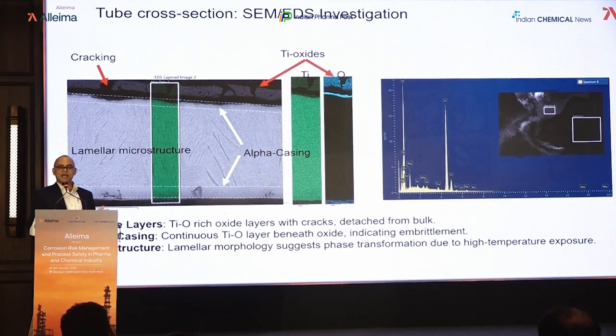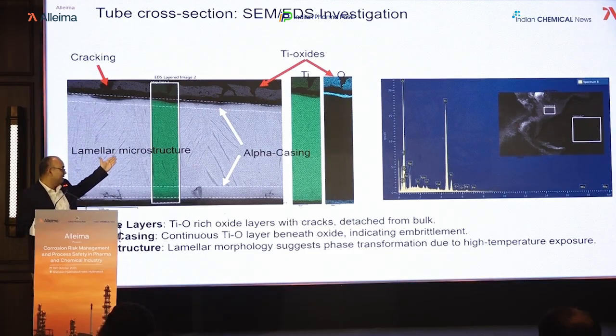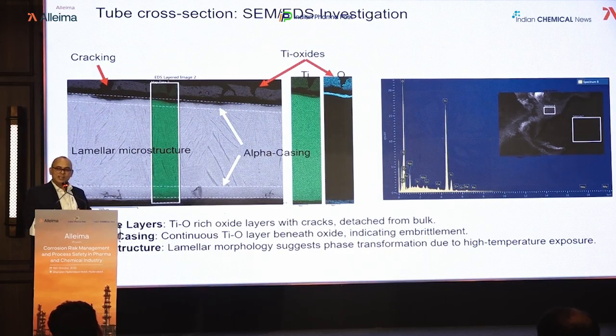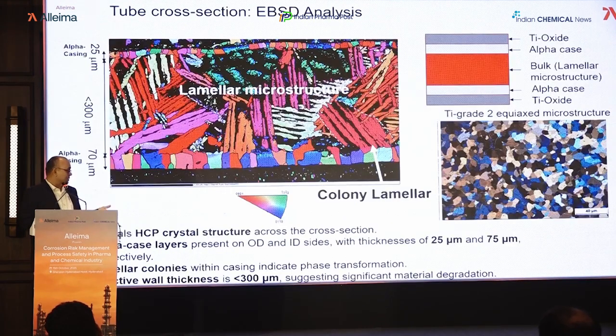So let's look into why it happened. Again, as usual, we do the same analysis: we take a small section and look at it under the microscope. What we can see is that there's a thick scale forming, which is titanium oxide. And in the cross section, the microstructure, if you know titanium, is very unusual. You don't expect that. Then again, it's not very clear, so there's another technique we discussed, that is EBSD. You get the colorful image, and you could see that.